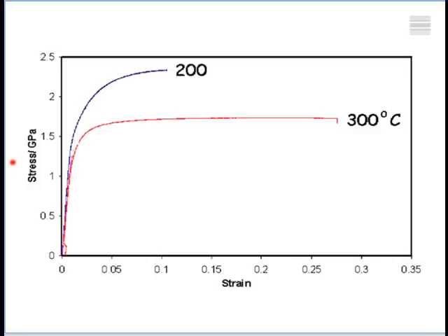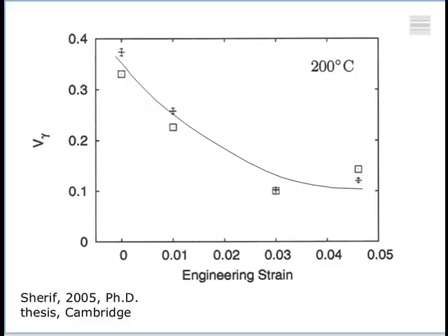Because the austenite will be mechanically unstable, it will decompose to martensite, giving work hardening capacity. This is a tensile test which is done in a reactor with neutron diffraction, and you can follow how the fraction of austenite changes as a function of plastic strain. And we repeated these tests for many, many samples. And fracture always happens when the austenite content reaches about 10%. Okay? Now, why is that? What is so magical about 10%?